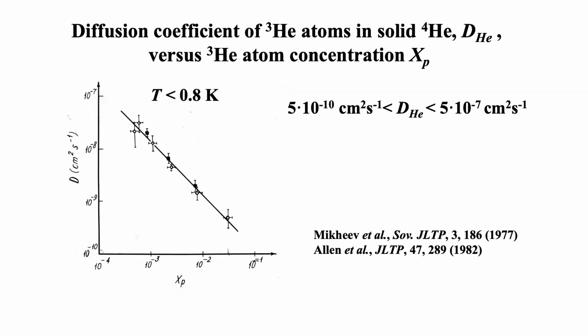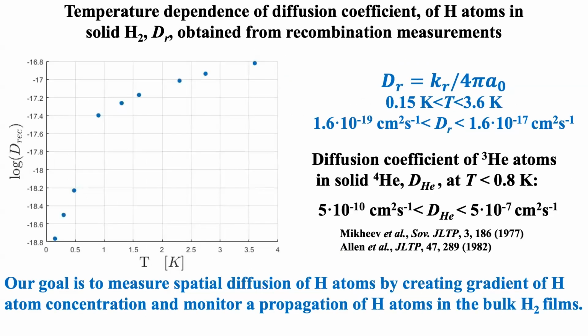When we compare these two numbers, we understand that this measurement is not right, because we are measuring the movement of the H atom, the slowest process in the movement of hydrogen. Our goal was to measure spatial diffusion of hydrogen atom by creating a gradient of H atom concentration and monitor propagation of H atom in a bulk, so that this atom doesn't go to each other, but they go to a place where tunneling is resonant.